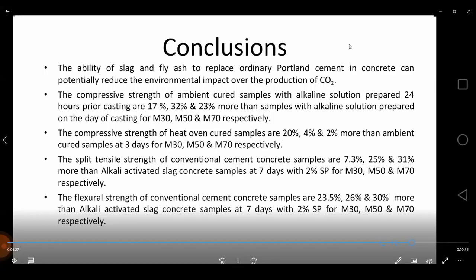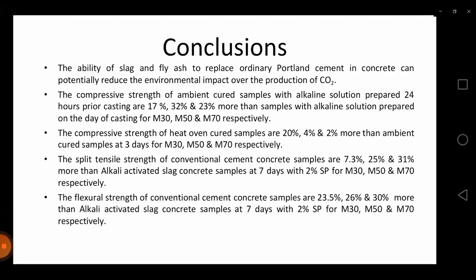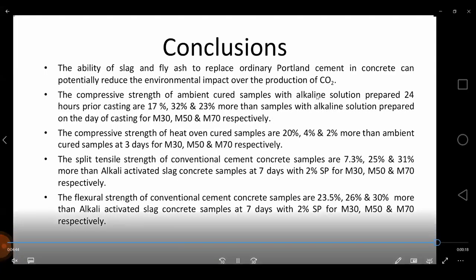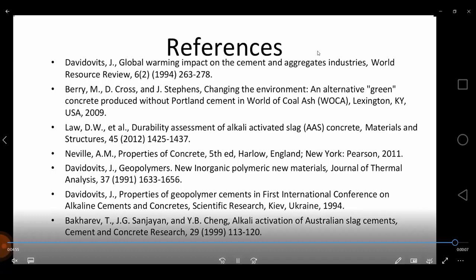The split tensile strength of the conventional cement concrete samples is 7.3%, 25% and 31% more than the alkali-activated slag concrete samples at 7 days with 2% of SP, again for the same mixes. The flexure strength of the conventional concrete is 23.5%, 26% and 30% more than the alkali-activated slag concrete samples at 7 days for the same grades of concrete. So these are the references I considered for the research work. Thank you, sir.